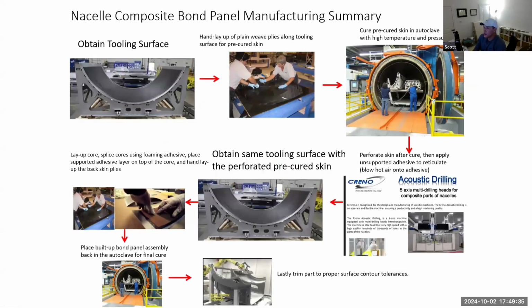All right, nacelle composite bond panel manufacturing summary. So how do we go about creating this honeycomb composite bond panel? Okay, step 1, obtain a tooling surface. Step 2, hand layup of plain weave plies along the tooling surface for the pre-cured skin. Step 3, cure the pre-cured skin in an autoclave with high temperature and pressure. Step 4, perforate the skin after cure. So after it's cured, take out the skin, perforate it.